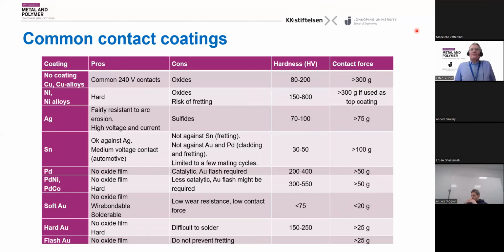So back to the different possibilities, I want to show you some common contact coatings. Of course, there exist other possibilities, but these are common, and I have in this table also shown some pros, some cons, common hardness intervals, and recommended contact force when using these materials. And the first coating is no coating at all. That means we will have copper or copper alloys as the contact material, which is common in household, as already discussed. They will have oxides on the surface. The hardness will differ depending on what type of copper alloy it is and how it's treated. So from soft to middle hard, and you need a high contact force.